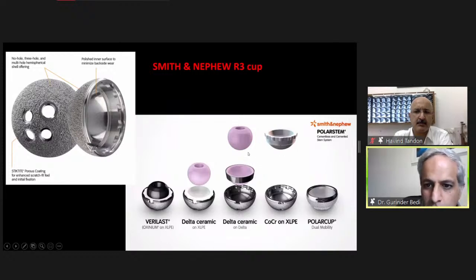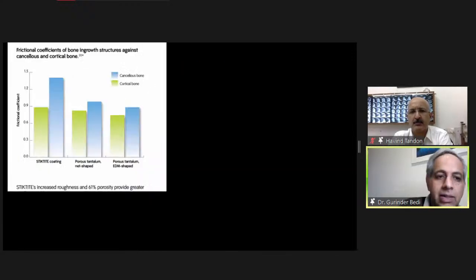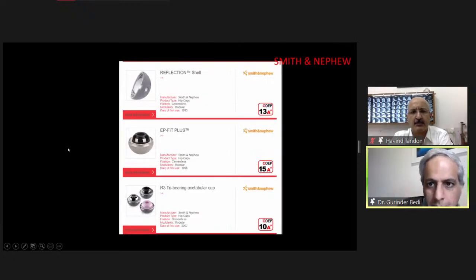The good thing that I can tell you about Smith & Nephew is a ceramic liner, which has a steel rim. A lot of times you will see chipping, which happens on the margin, and once the chipping starts, the liner can actually go, but the metallic rim really helps stop it. How good is the STIKTITE coating? You can actually compare it in terms of the frictional coefficient between tantalum and STIKTITE. So it's a good material to use.